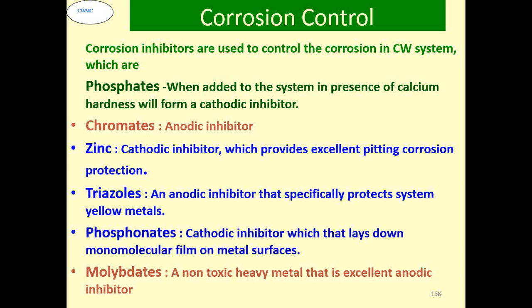Triazoles are generally used for the yellow metal, that means the brass, copper based systems. Phosphonates, they are very good cathodic inhibitors, and they lay down the monomolecular film on the metal surface, and in combination they are very good antiscalant as well as corrosion inhibitor. Molybdates are very good corrosion inhibitors, but of course they are toxic, heavy metal, so use is limited. There are certain nitrites which are used, especially in the closed water system, like your car coolant, that also contains nitrite based inhibitors.